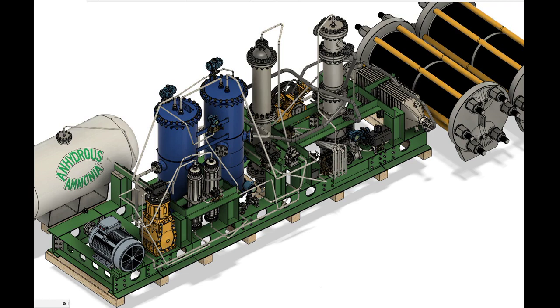The major advantages of using an ionic liquid are eliminating all contamination of the synthesis gas, achieving superb tribological performance permitting nearly friction-free compression, and dramatically increasing TBO and its attendant levelized capex. Ionic liquids also feature very low compressibility, reducing mechanical losses. In addition, most ionic liquids have high viscosity, enabling leak-free design using standard seals. They also have low corrosivity against stainless steel. An additional advantage of this compression technology is its drastically higher compactness, allowing even higher capacity miniature ammonia plants to be fitted inside the volume of the 20-foot ISO container.